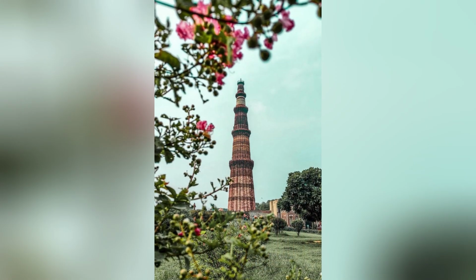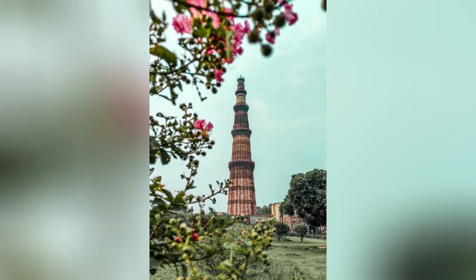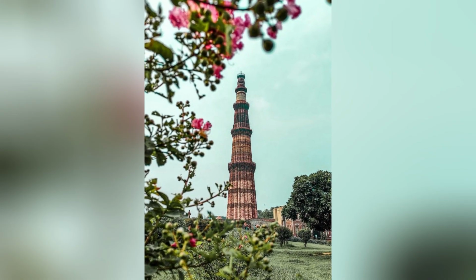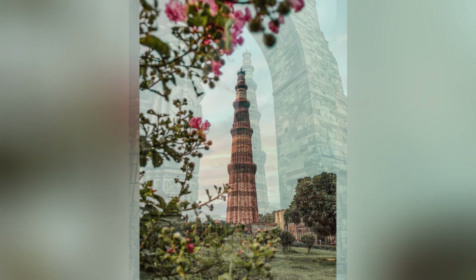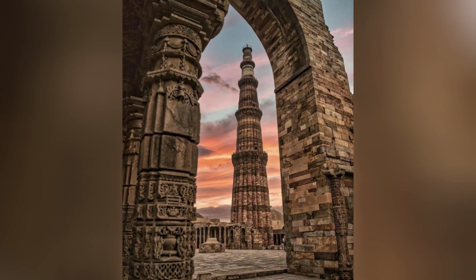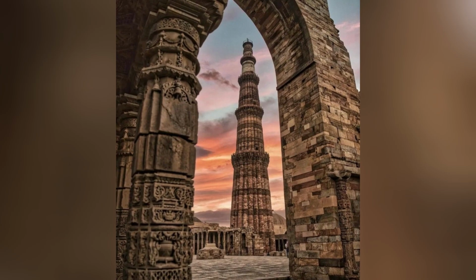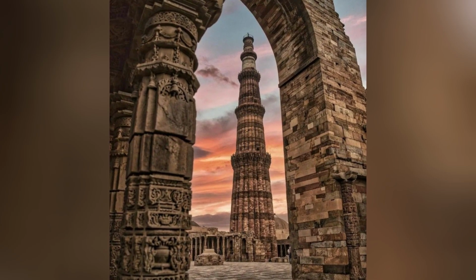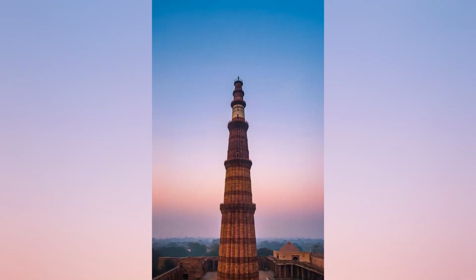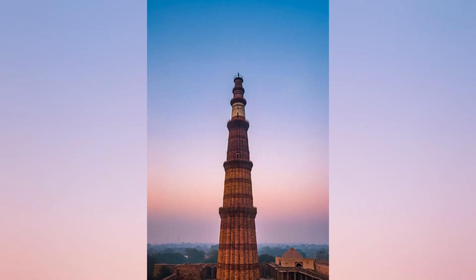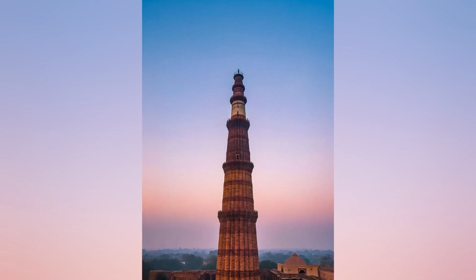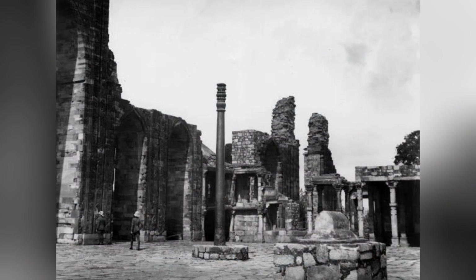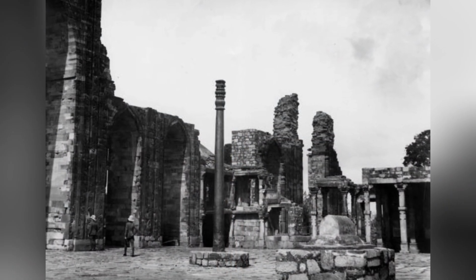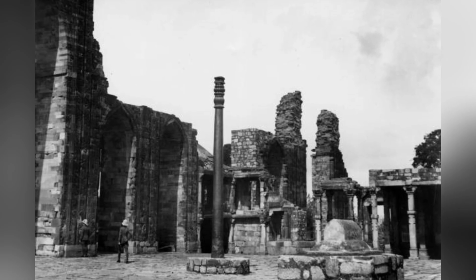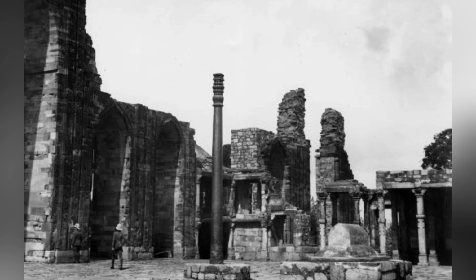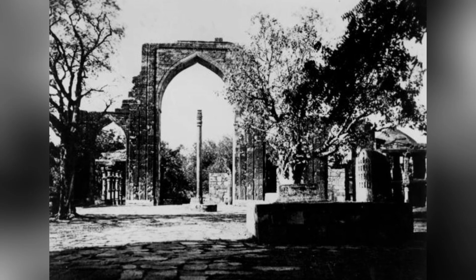The formation of the protective film on the pillar is not a simple one-step process, but a complex multi-stage process that involves the initial formation of a porous, partially protective layer, the gradual densification and sealing of this layer over decades and centuries, and the eventual development of a fully protective film that reduces the rate of corrosion to negligible levels. The understanding of this multi-stage process has important implications for the prediction of the long-term performance of modern iron and steel structures, because it suggests that the early stages of corrosion, which are typically used to predict the long-term corrosion rate, may not be representative of the long-term behavior of the material.